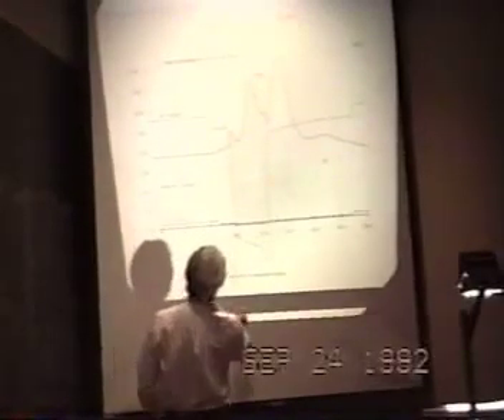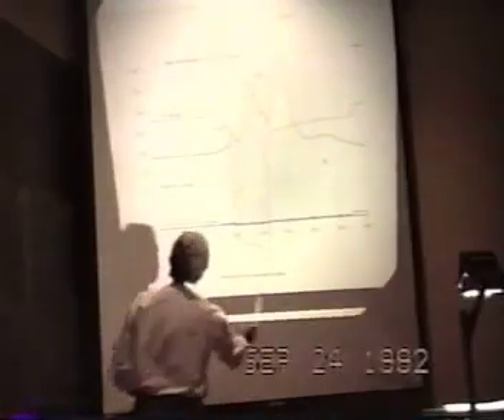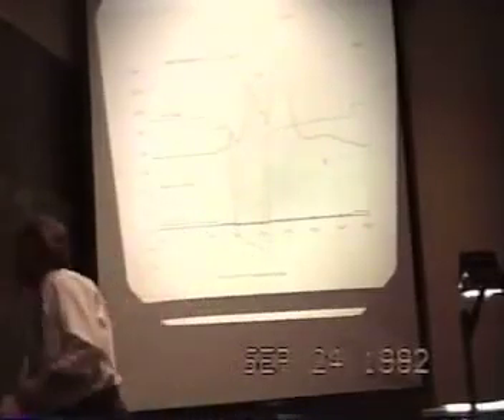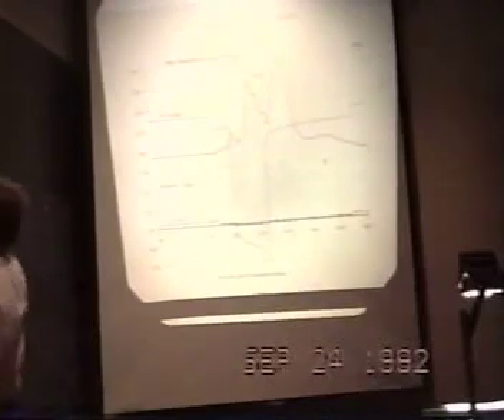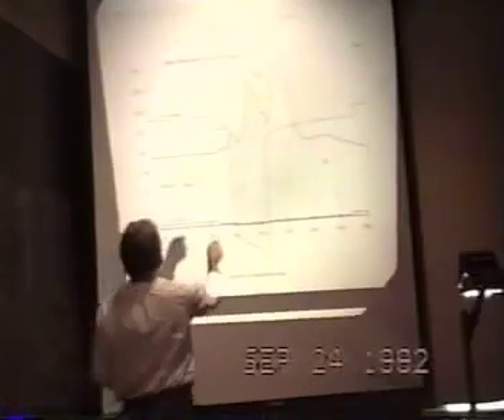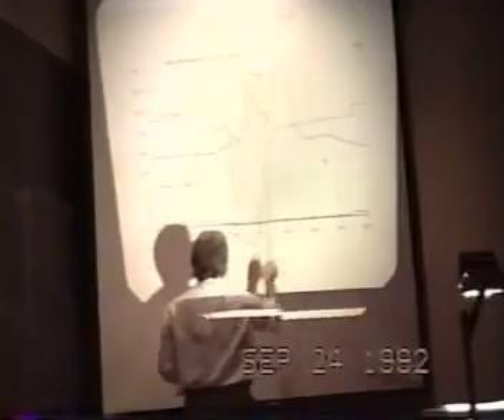So here we have a time at which we've first stepped the current down to low values, reversed the current. The cell voltage follows this profile on the reference voltage. The interesting thing is that, so the resistance ratio versus loading curve looks like this. As we strip the cell, we expect to see the resistance go over its maximum and come back down the other side. Instead of doing so, in the case of cells to which boron has been added, we see two maxima during the stripping and two maxima again during the reload.